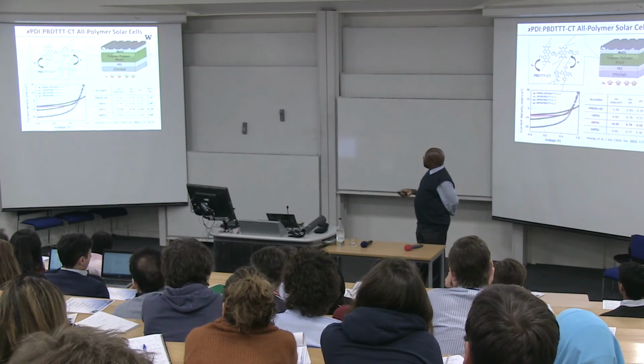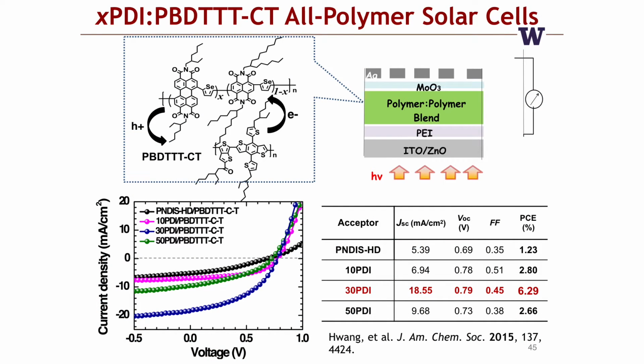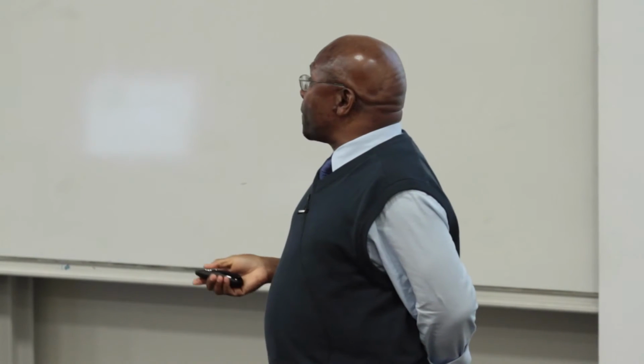However, in device performance, it turns out that the 30% PDI in combination with the same polymer in all of these gave the best result, as shown here. In fact, more than a factor of 5 enhancement in the efficiency by finding a way, in this case, through random copolymerization, where we are able to regulate the crystallinity, we are able to achieve more compatible polymer blends in making all-polymer solar cells.